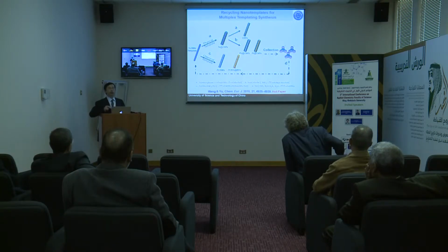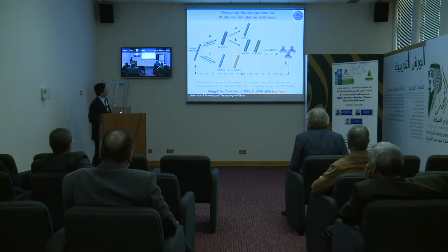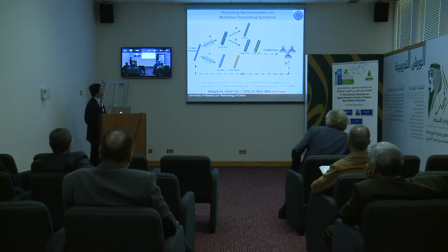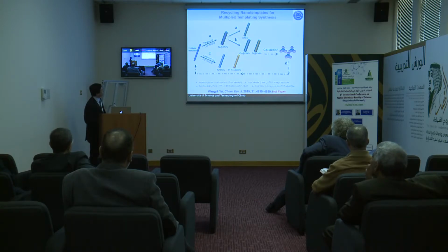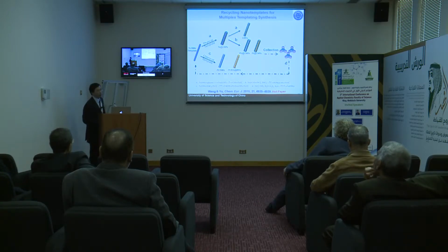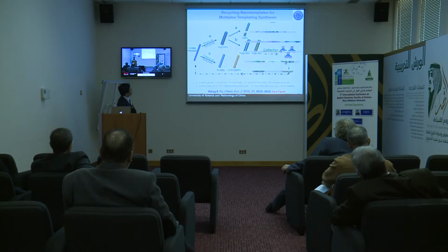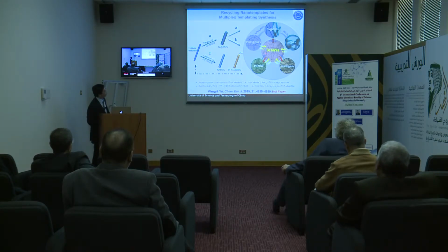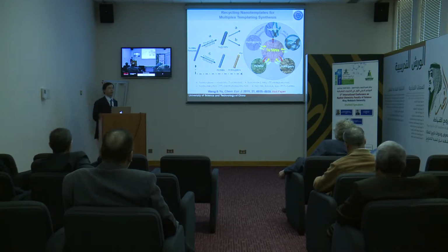Then the question is, can we recycle this template? We synthesize tellurium nanowires just from the sodium salt of ionic tellurium species. So we synthesize these ionic species into nanowires and use them as a physical template or chemical template. After that, if you etch them, you can collect these ionic species again, so you can do this recycling process. Some of the data showing this look very promising for recycling these tellurium nanowires in the chemical synthetic system, so that you can reduce the cost of using this kind of nanowire template in the future.